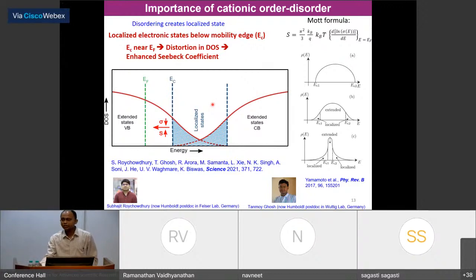For example, disordering can create electronic localization by charge scattering, which was proposed by Anderson a long time back. This Anderson metal-insulator transition is well known in solid state chemistry and solid state physics. I can simplify Anderson localization by invoking the concept of the mobility edge, using this simple schematic of a semi-metallic electronic structure. The mobility edge separates the localized states from the extended states. EF is the Fermi level, EC is the mobility edge. Localization happens due to charge carrier scattering at the disordered sites. If EC, the localized states, moves towards the Fermi level, electrical conductivity decreases. And when EC goes below EF, the system becomes an Anderson insulator.